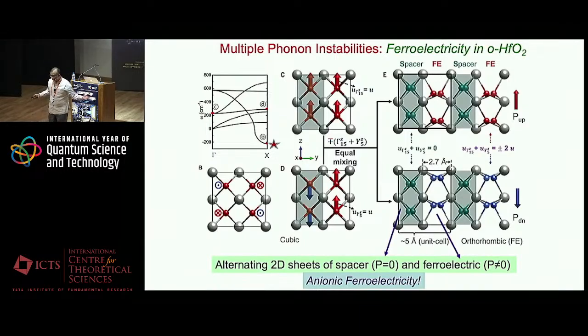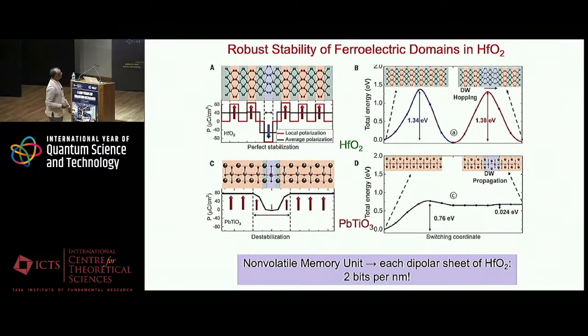It's an anionic ferroelectricity, unlike the perovskites where it's driven by the transition metal. The second very remarkable aspect of this ferroelectricity is that even if you switch one dipolar sheet in the opposite direction, you get an energy which is very comparable to the ground state.